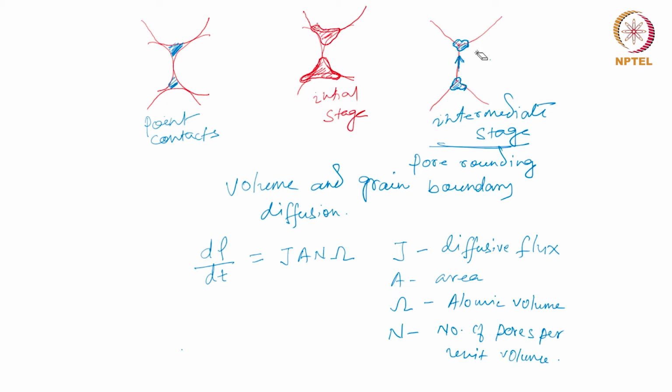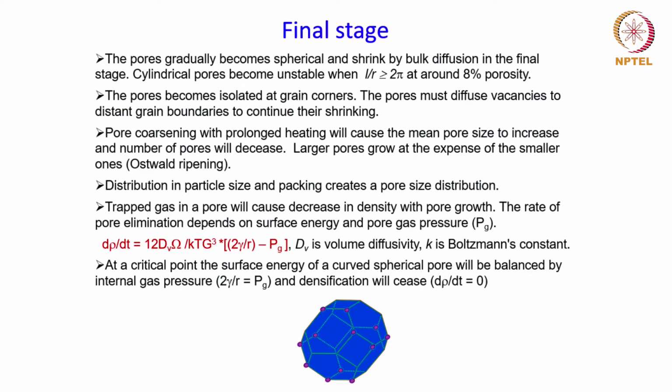And although surface transport is active as indicated by the pore rounding, these surface transport mechanisms do not really contribute to the shrinkage or densification. So this is something that we have discussed before also, that surface transport mechanisms are actually non-densifying mechanisms. So now let us move to the final stage.